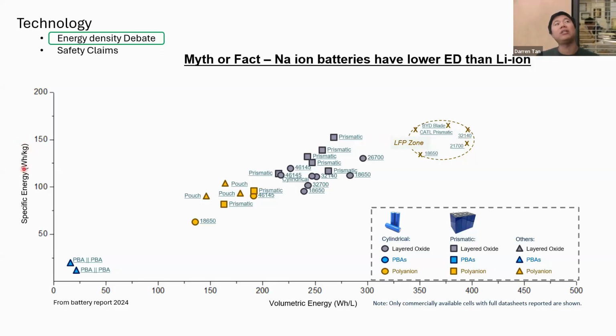And that's where a lot of the news reports focus on watt-hours per kg. But what's often not reported is the watt-hours per liter point, where you can see a stark difference, right? Some of the polyanion chemistries are even less than half the volumetric energy density of LFP. So I would say, at least with today's data sets, sodium ion in general does have a significantly lower energy density than lithium ion. There's a lot of work being done to improve this, but if we simply draw from commercial products today, this is the outcome we have.